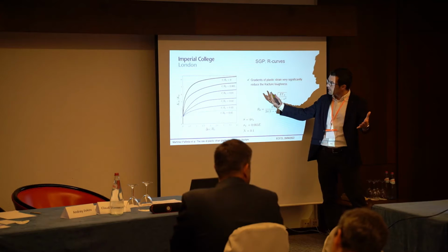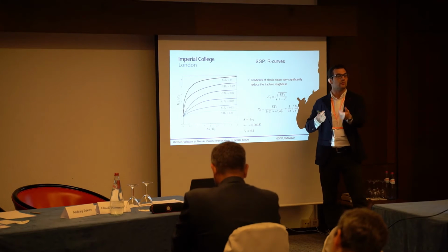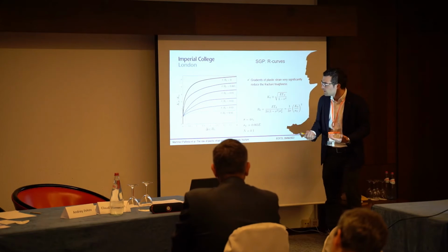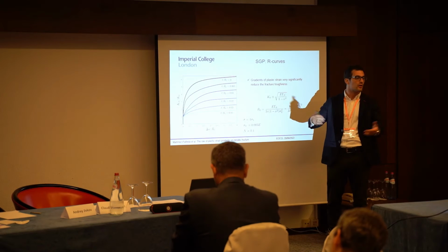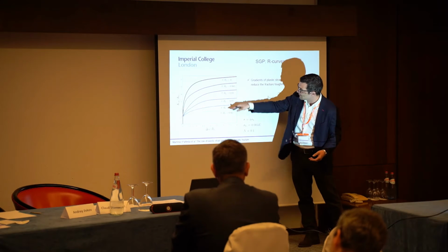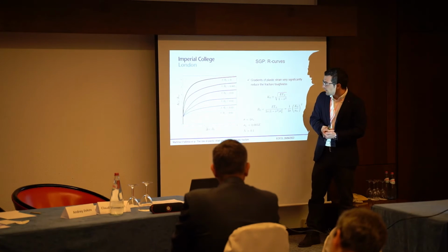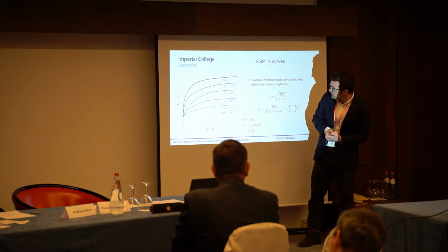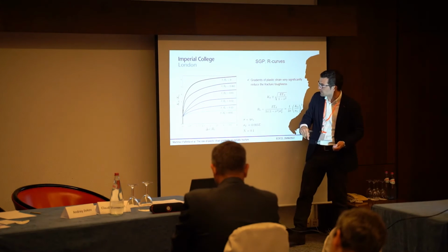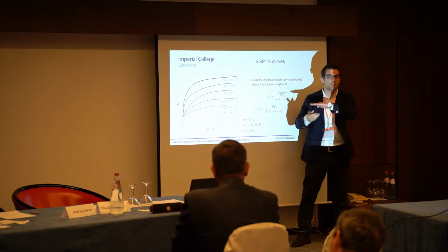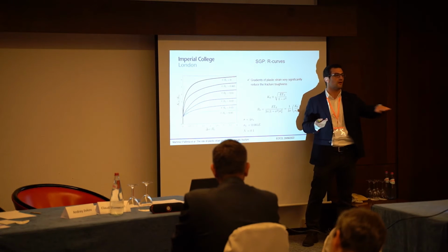And again, as you would expect, you will see that as you increase this ratio between the length scale and the fracture process zone, you get higher strain gradient effects, you get higher stresses, and you bring up the crack growth resistance. The next thing that we did was, if you look at these R curves, what you will see is that at the end you reach a plateau. This is what we call the steady state fracture toughness.